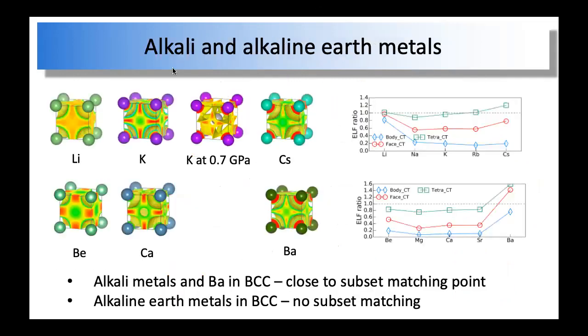Okay, so here is the thing. Let's say the alkali and alkaline earth metals. For alkali metals, it is very clear. This shows the ratio between the value of the ELF at the midpoint and the value at the edge center. For alkali metals, they are all very close to 1. And in some cases, for example cesium, the maximum point is actually already at the midpoint. That means cesium at 0 GPa is already at the perfect subset matching point. And for lithium, it's also very close.